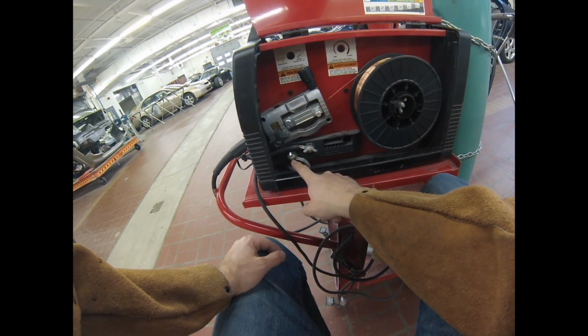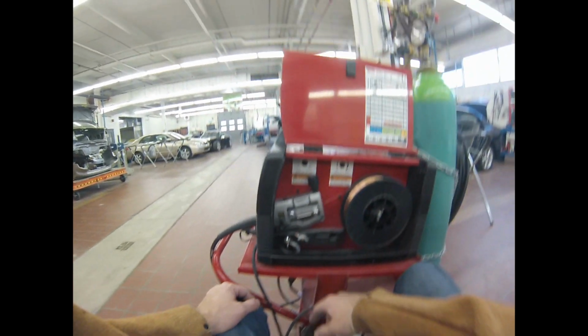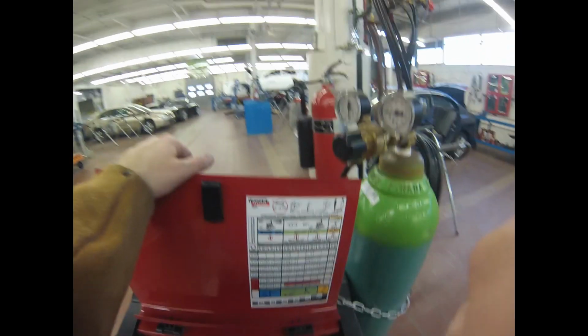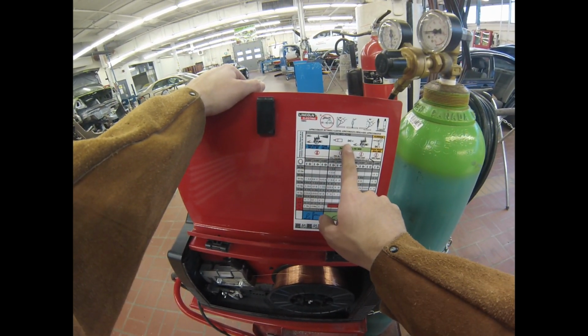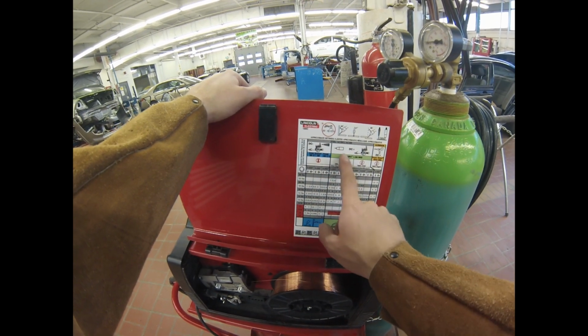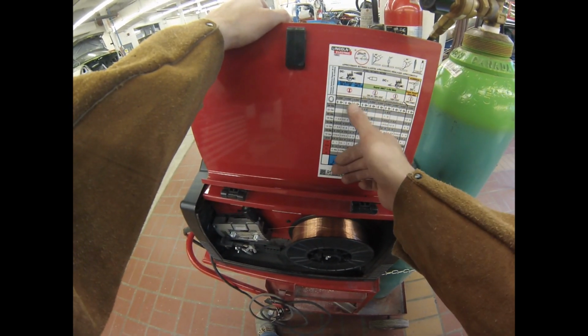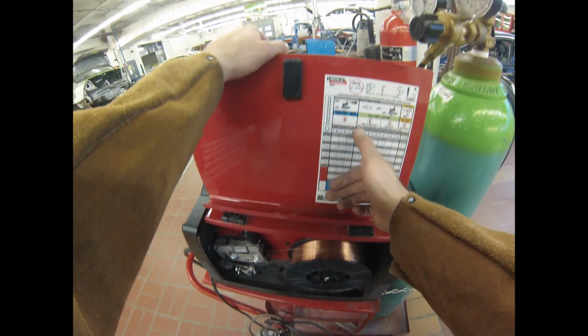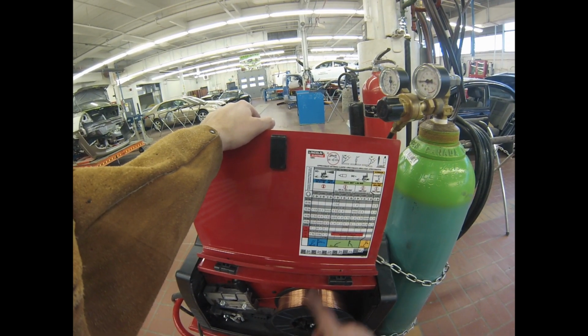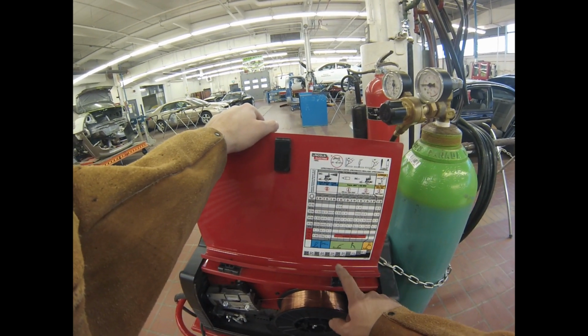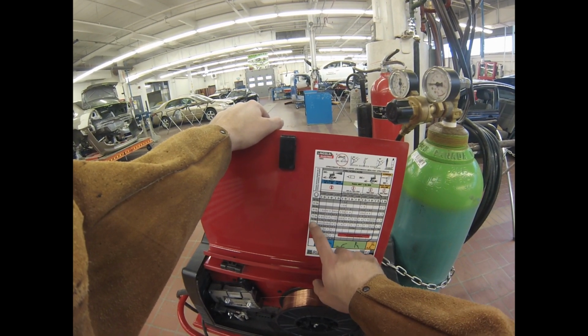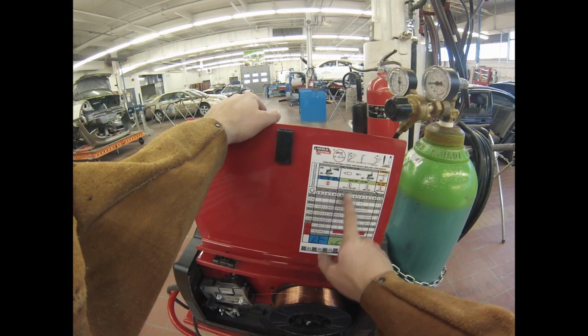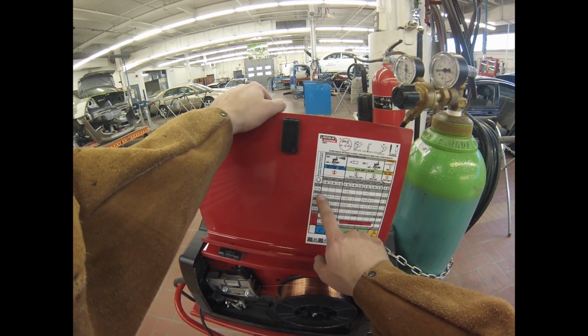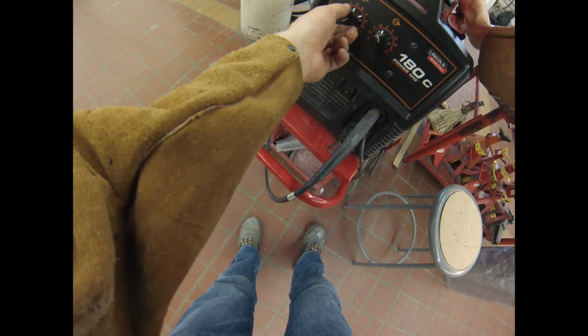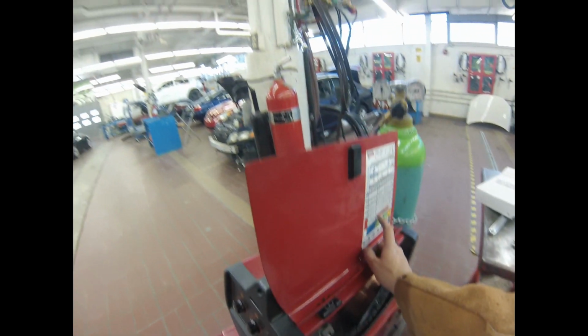These are the continuity connectors, so you can make it negative or positive. It's a DC welder. So if you look at this thing here, it's like the little cheat sheet. You can set it up DC negative, DC positive, or DC positive even for aluminum, right? So we're using the mixed welding gas. We're running 025 wire. So this is sort of like a cheat sheet for you, a little welding setting and setup. So it's saying like if you're welding 20 gauge metal, right, 24, 22, 20, you're using the mixed gas with 025 wire, you want to start around 1.5 and D. So you would set it to D and 1.5-ish, and then you'd tweak from there, right?